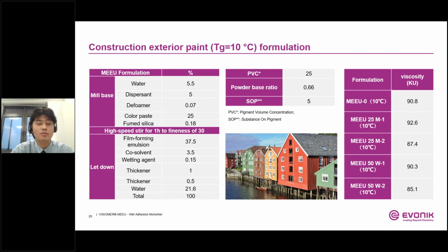And here comes our formulation. The table on the left side shows our guide formulation of construction paint. Most additives are provided by Evonik Tego products. The film-forming emulsion in it is the series of emulsions we synthesized before, and accounts for 37.5%. Based on the typical experiments in construction paint formulations, we designed the pigment volume concentration at 25, powder base ratio at 0.66, and SOP at 5. The viscosity of all formulations was controlled between 85 to 95 KU.